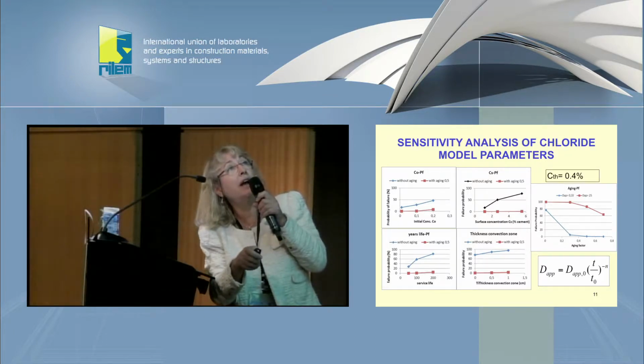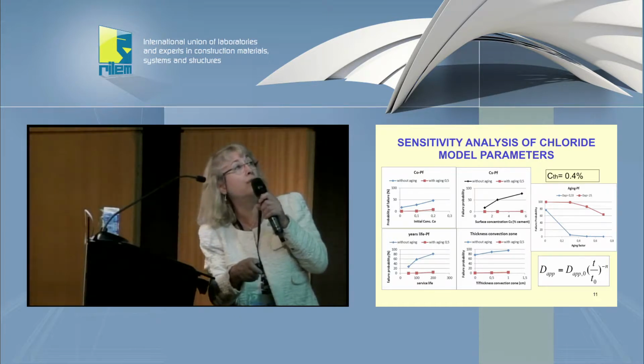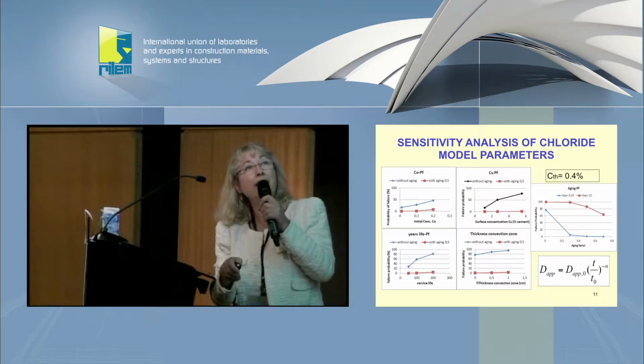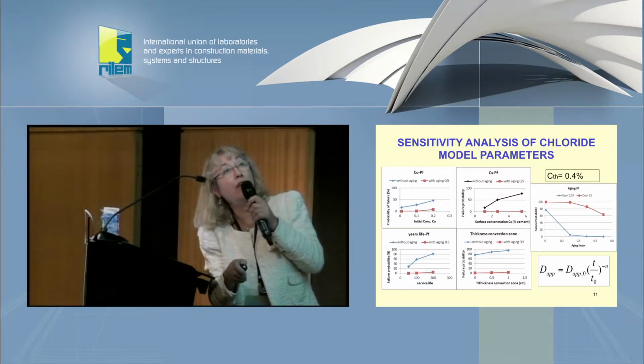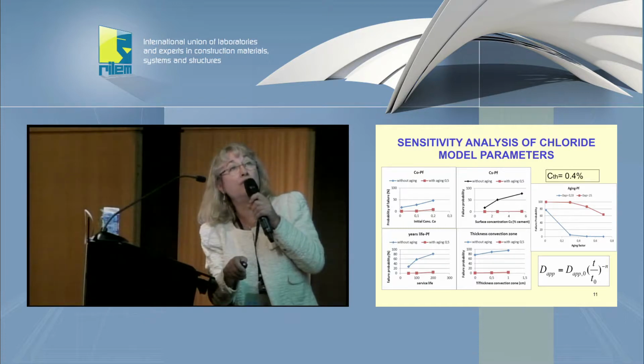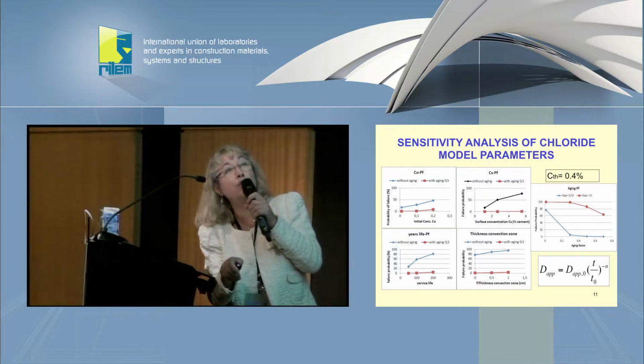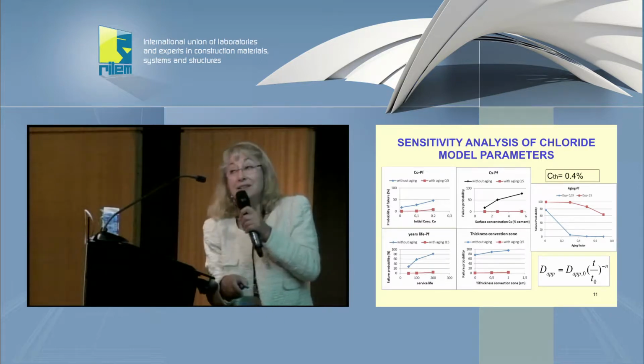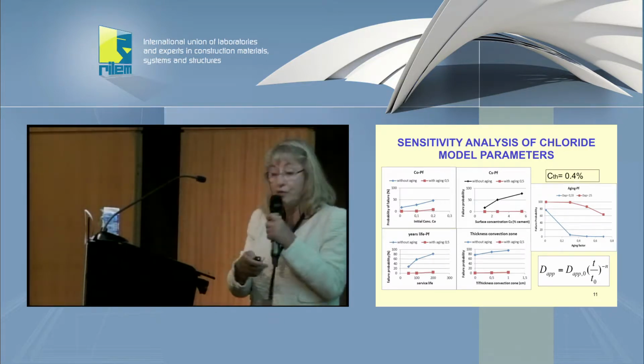However, if you don't have this aging, the effect of the different parameters, it can be seen here comparatively, is very high. For instance, the surface concentration, the thickness of the convection zone is not too important. The years of life, of course, is important, 50, 100 or 200, but the critical one is the aging factor. As soon as, for instance, with a low diffusion coefficient, you just introduce an aging factor, the probability fails completely from very high to almost negligible. And it's also clear here with a much higher diffusion coefficient of 25. In that case, this is the controlling parameter of this equation.